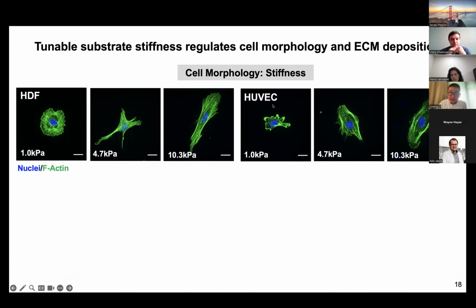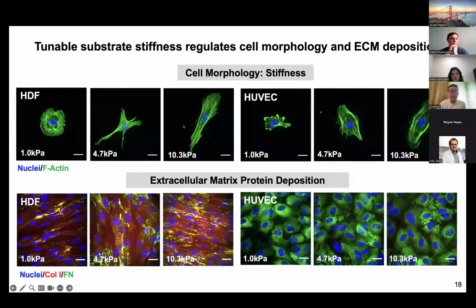And then HUVECs, which is interesting. We see the behavior, but I think for a different cell type, you have a threshold of the maximum mechanical property they can sense. Increasing from 1 kilopascal to 5 kilopascal, you can see that they go from nascent adhesions to more defined cobblestone structures with really defined stress fibers. However, when you increase from the intermediate stiffness to really stiff hydrogels, they don't seem to have significant differences in cell morphology. So again, we are looking at the cell morphology.